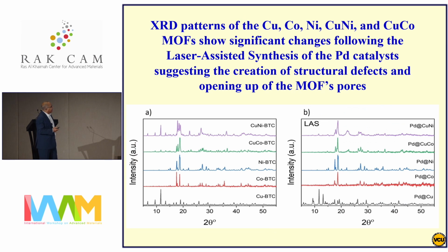Turning to the activities, before we look at the activity, I want to show something important here: the X-ray diffraction of the MOFs. This is the support as synthesized, on the left, and then we use laser irradiation in solution to reduce the metal ions in water, with the MOFs present.